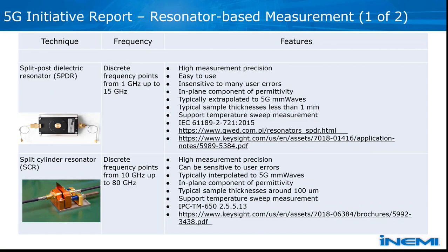The next one, the split cylinder resonator, also operates at discrete frequency points. So we have a single device at a single frequency, but this one spans up to higher frequencies. It also gives us high measurement precision. It delivers information about the in-plane component of the permittivity, and similarly to SPDR can support temperature sweep measurements. From those two, we treat the SPDR, which is in the lower frequency range, as a kind of reference method.